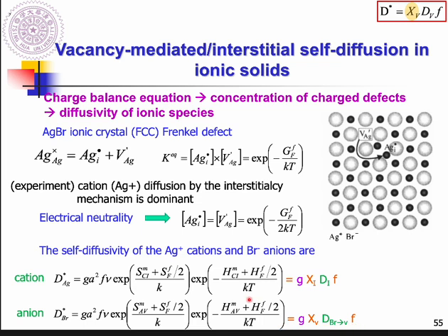Okay, so write it down and fill in each one. The fraction of vacancy at the silver site will be the Frenkel defect formation Gibbs free energy divided by 2, separated into enthalpy and entropy terms. And the diffusivity will be, as I mentioned, a square f mu, migration energy. This migration will be silver migrating to the self-interstitial site. And for bromide, the same idea.